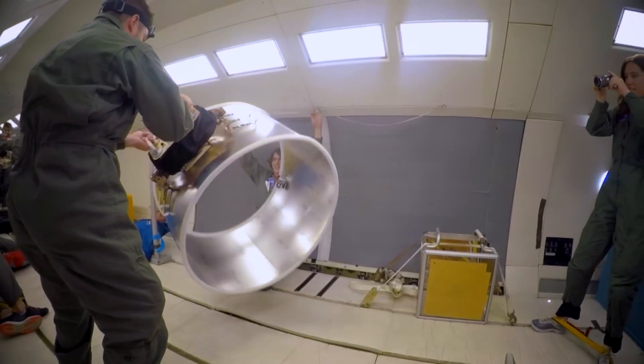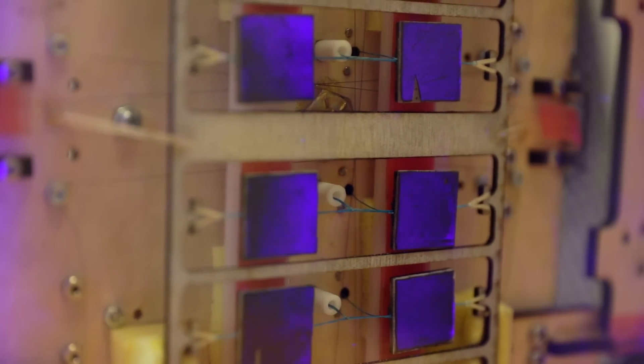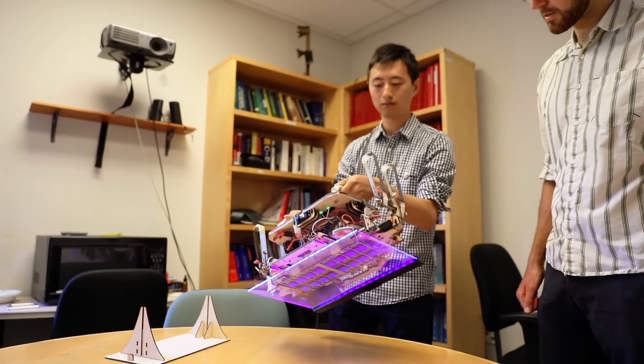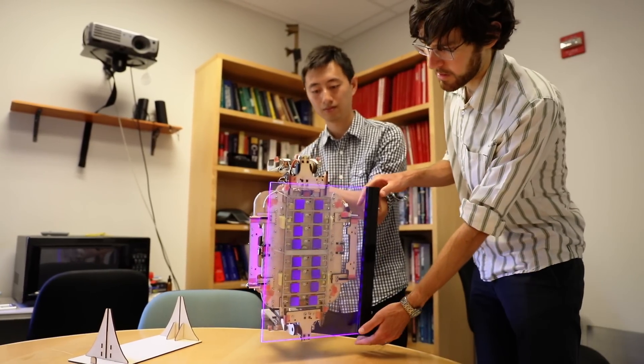The type of adhesive we use is space qualified — it remains sticky even in the very challenging environment of space. Traditional methods of grasping like suction cups don't work because there's no atmosphere, and anything sticky — called pressure-sensitive adhesives — becomes brittle in the cold and no longer sticks.